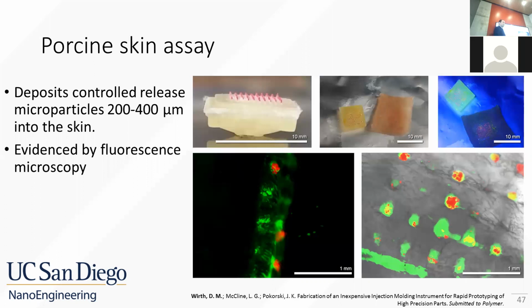Using these dye-loaded microneedle patches, we conducted a porcine skin assay. We pushed the patch into a bit of pig skin, and parts of the microneedles dissolved into the porcine skin. You can see the results: we're achieving 200 to 400 microns of penetration into the porcine skin, and these microneedle patches are depositing their microparticle payload into the simulated skin.